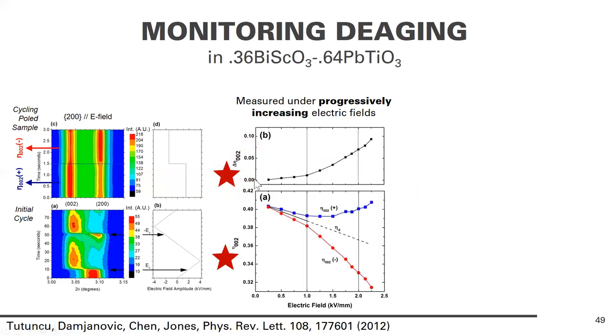And if you start looking at this data, you might get excited because it increases as a function of field amplitude. And those familiar with Rayleigh law may suggest fitting different parts of this to a line. But there's an interesting effect that's not captured in this type of representation, and that is the absolute value of eta. The absolute value of eta during the positive field is shown here, and during the negative field is shown here. And what you're seeing on average is a decrease in the degree of poling while you're cycling the sample.